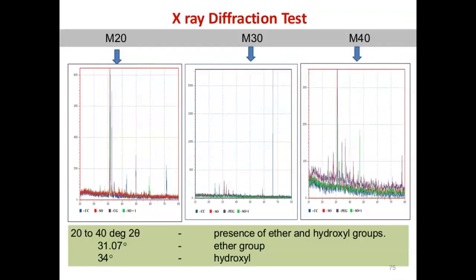Another one is X-ray diffraction analysis. Here you can see the peaks between 20 and 40 degrees on the x-axis, 2 theta. When the peak comes between 20 and 40 degrees, that shows the presence of ether and hydroxyl groups. 31 degrees shows the ether group and 34 degrees shows the hydroxyl group. In M20, M30 and M40 concrete, in all cases the peaks are there between 20 and 40 degrees. That shows the presence of hydroxyl ether, which shows that it has the capacity to hold the water and stop water evaporation.